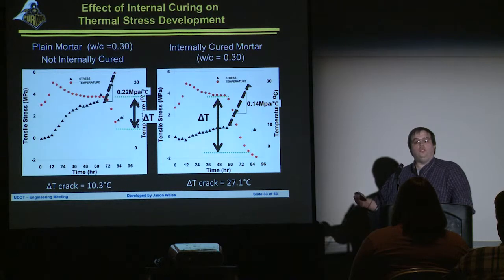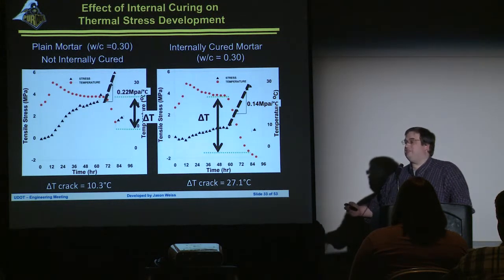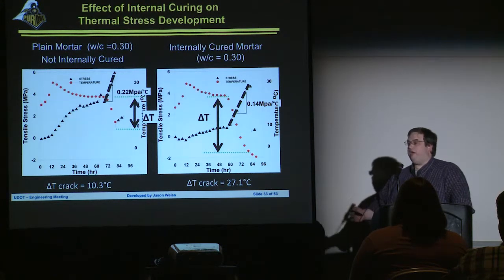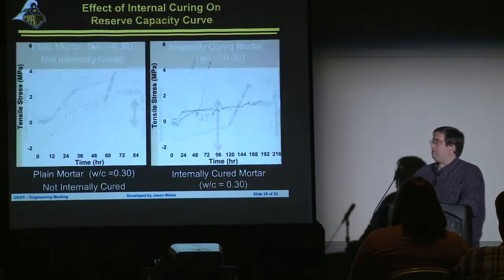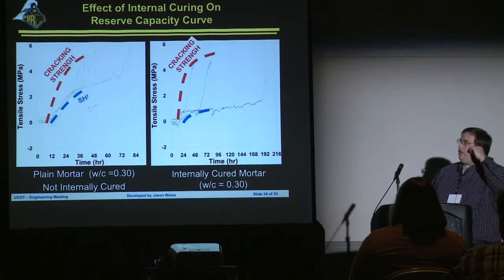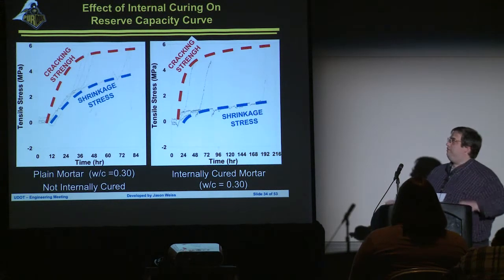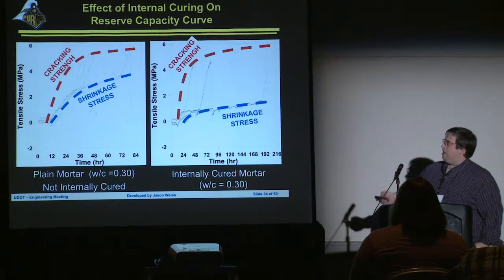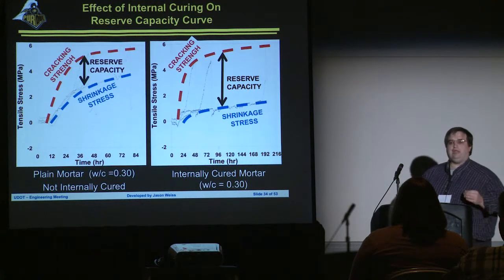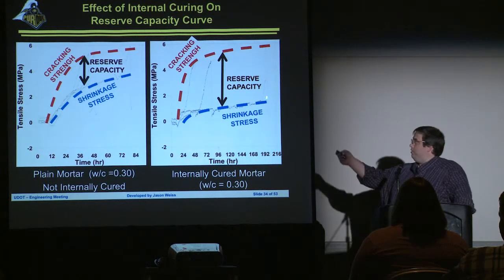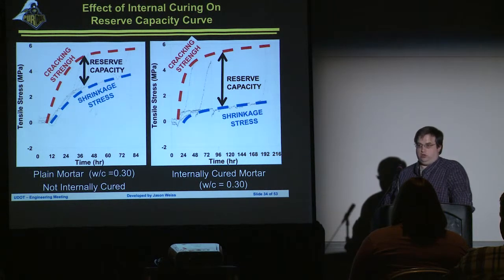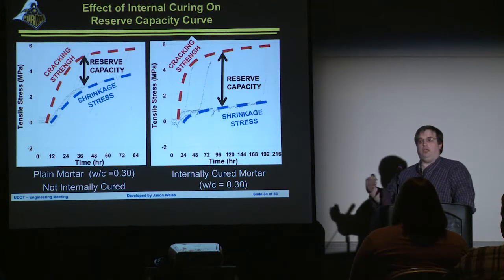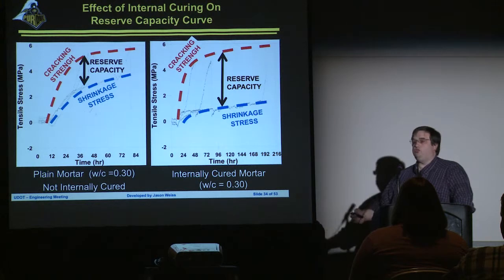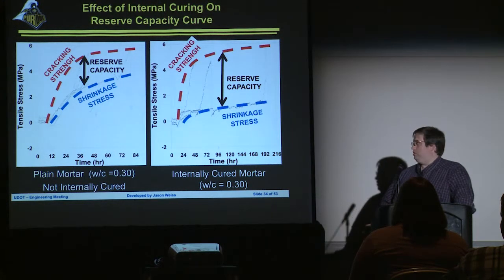In addition, we change the stiffness of the concrete because we now have a system that's a little bit less stiff. And by having a system that's a little bit less stiff, we have benefits in that we're not building up as many stresses inside of the overall system. Now, you can go through and you can do this at many different ages, not just 72 hours. And you can see that we dramatically increase the reserve capacity when we start looking at internal curing. This means we can have a greater temperature swing, greater loads applied to the system before we would start seeing cracking.